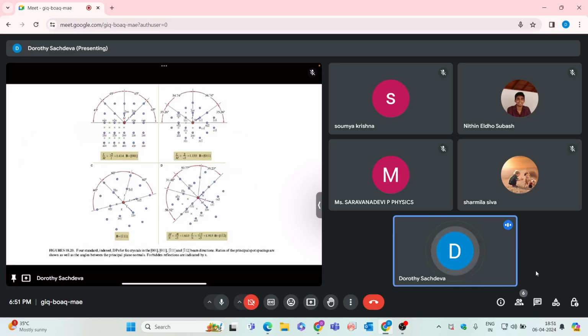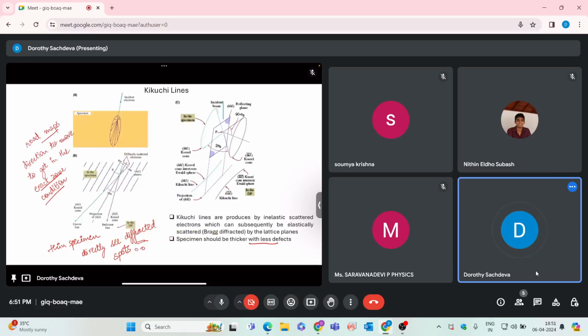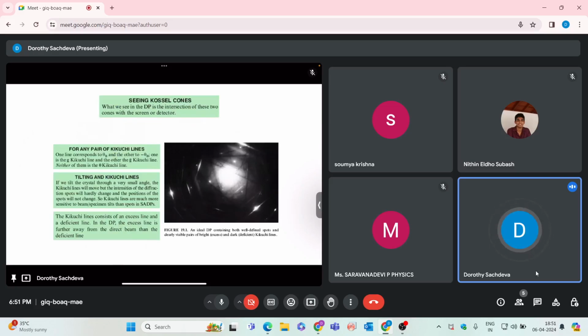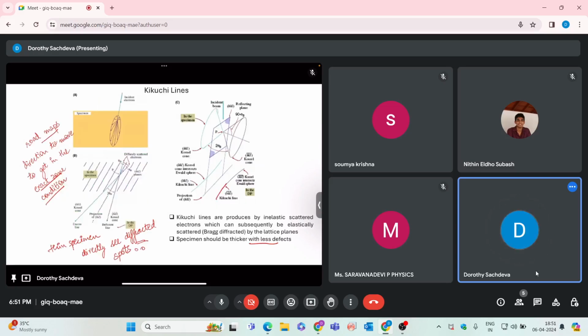If you are slightly away from the zone axis, then you will see some distortions in your diffraction pattern, and that could be misunderstood. So you always need to go to the exact zone condition and then determine the diffraction pattern, and that will be done using these Kikuchi lines. So Kikuchi lines, we know, are these two lines. One is this excess line and one is this deficient line.